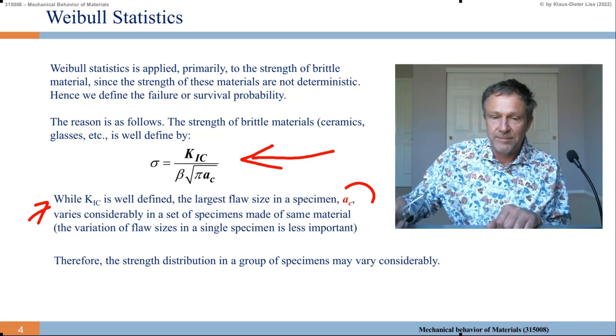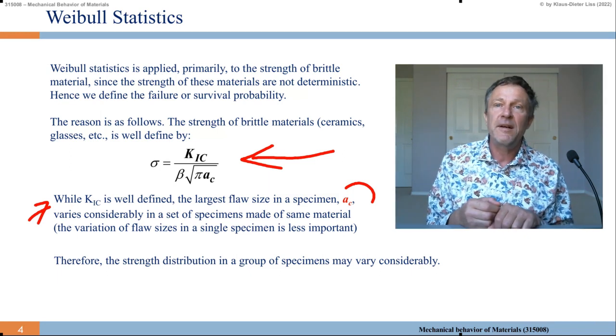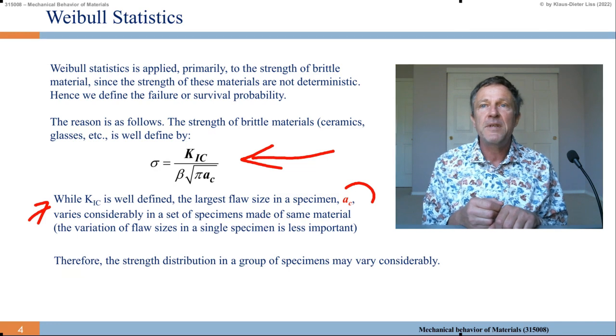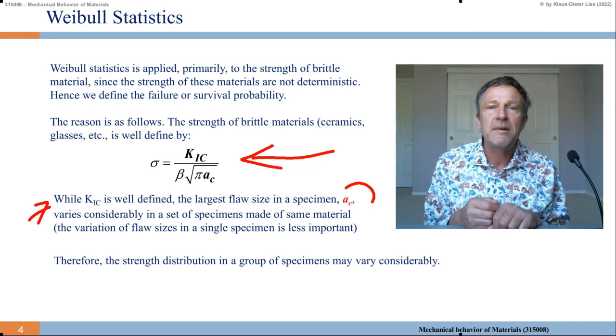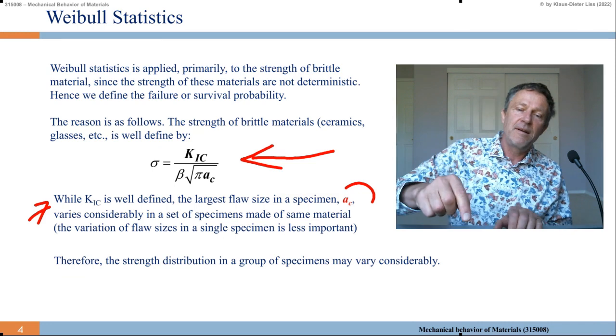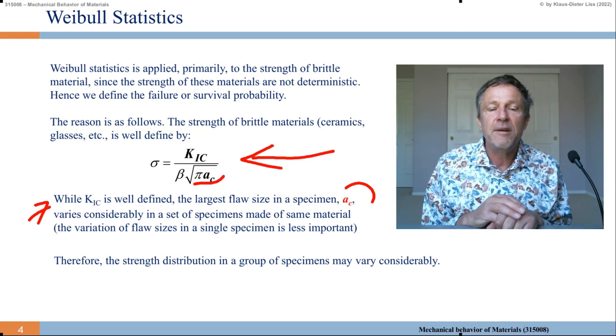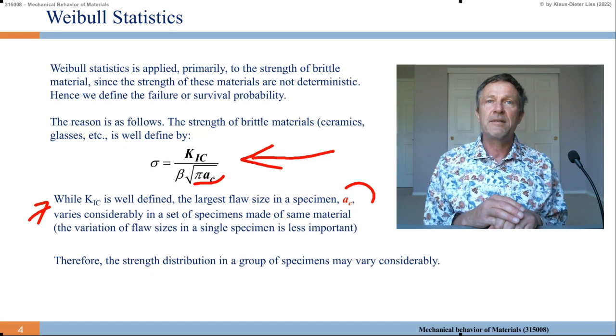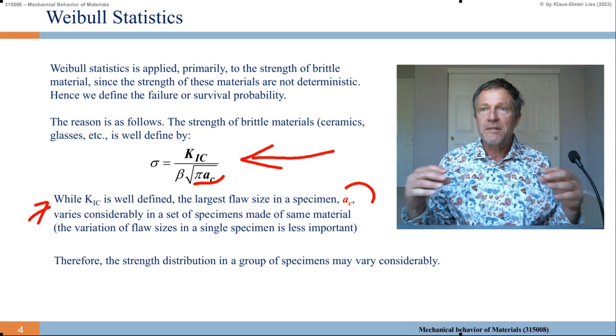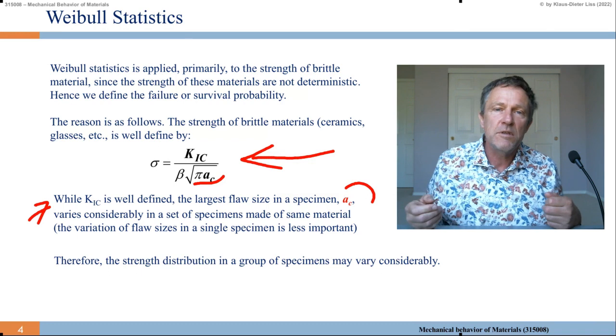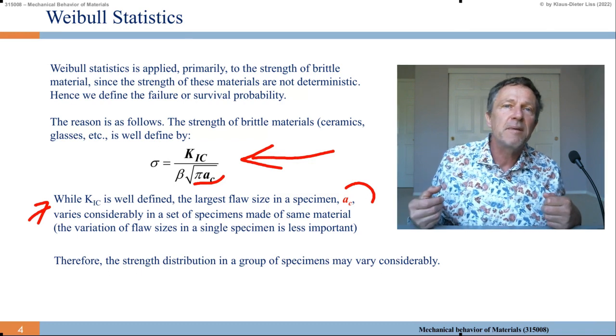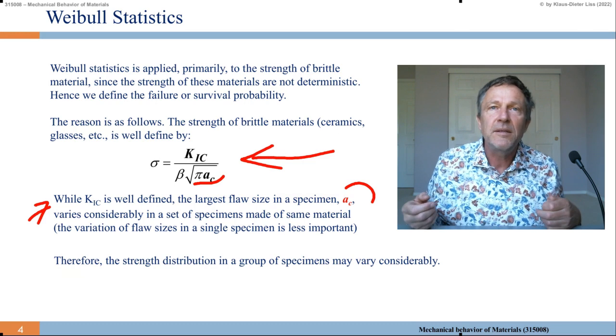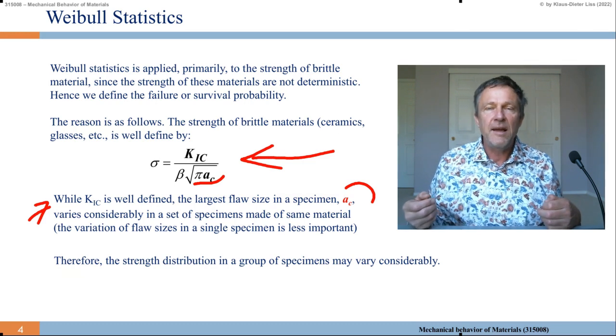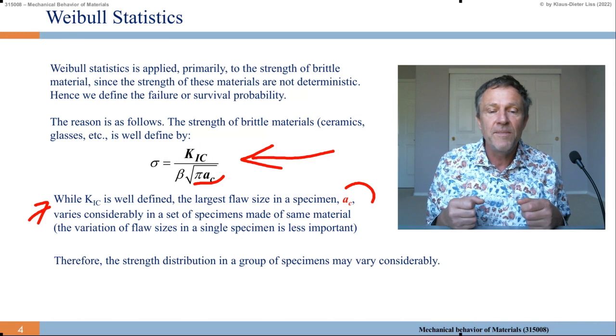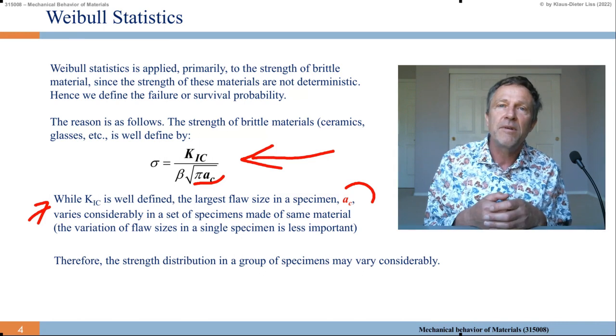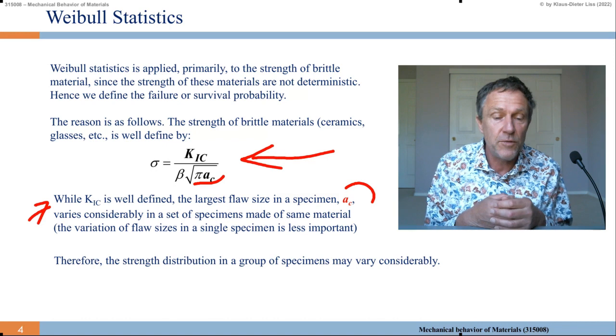So what does it mean? If we have a given material, let's take some window glass, it may have some inclusions, it may have some cracks, it may have some bubbles inside. And these, through the a, determine a critical stress sigma as given by this equation. So now these sizes of bubbles or inclusions, precipitates, soft precipitates in steel, like sulfides, they lead to crack stress concentration and eventually may lead to crack initiation and propagation, as we know already.